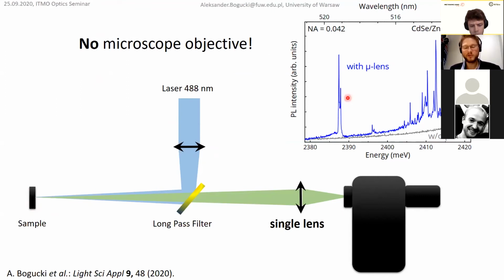So the object that has 5 nanometers in size, right? And what is even more important, we can come back to the same nanoscale object, because the microlens itself is quite big. I will elaborate on that a little bit later as well. But for me, as an experimentalist, it's very appealing, because you can measure something which usually is very difficult. For example, it's very difficult to come back to the same quantum dot if you don't have markers and you don't have some experimental setup that will allow you to precisely determine where these markers are. And here, if you print only one microlens on your sample, for example, and there is a quantum dot under this microlens, then you can, without any additional equipment, measure it again and again and again, and you can easily find it, because this is the only place on the sample that will have a strong sharp line.